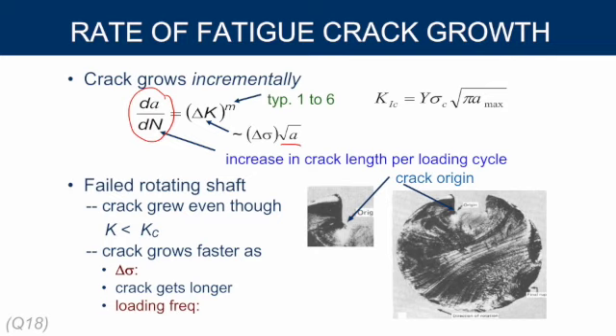Okay, so we can model that, like I said before. There's a toughness value that can be defined for any material, K sub c. That number is essentially constant, but it's the crack propagation that changes, and that's related inversely to the stress that the material can handle. And this says sigma c is the critical stress, so essentially is the yield stress that would cause failure. Okay, so what happens here is even though the K may be smaller than it was the material originally had, over time that will grow and the cracks will propagate.